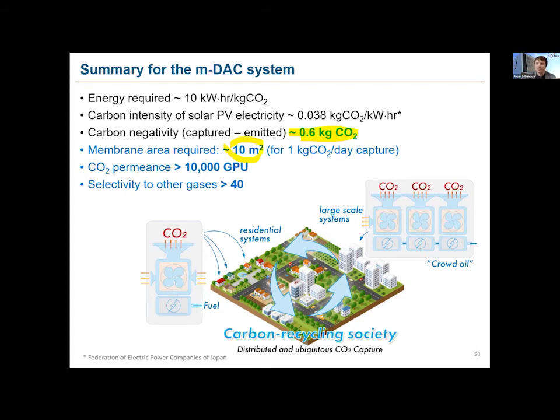Well, you know, these numbers are presented in order to understand how much it will take for 1 kilogram per day capture. But this system is not limited. What we are designing in Moonshot is a home-based system, residential, which will capture 2 kilograms. And we calculated 2 kilograms from approximately the amount of natural gas which we are now using at homes. So in order to offset that, when we will start using CO2 by putting it back. And this number is only to give you an impression how much power it will take for 1 kilogram, but you can scale up, of course. In a home, it will be a few kilograms per day, maybe 4 to 5 kilograms. In a company, or in a school, for example, it may be 1 ton per day. So the system is actually scalable.